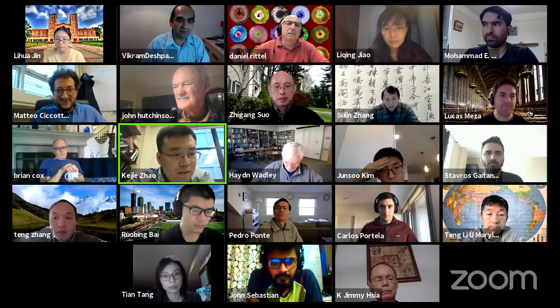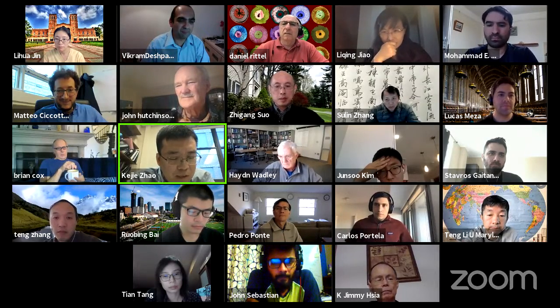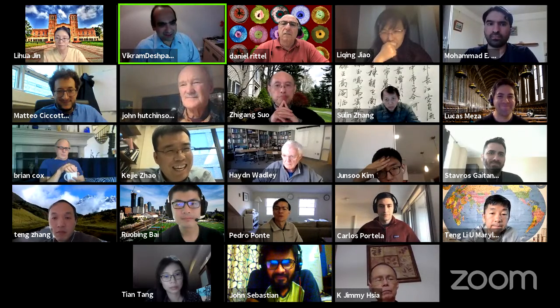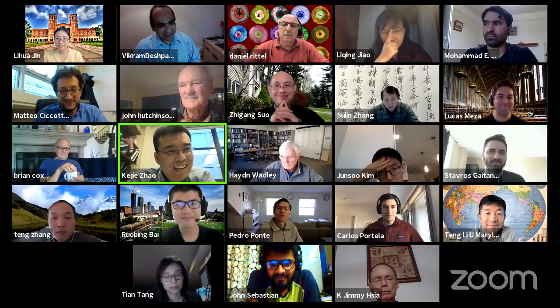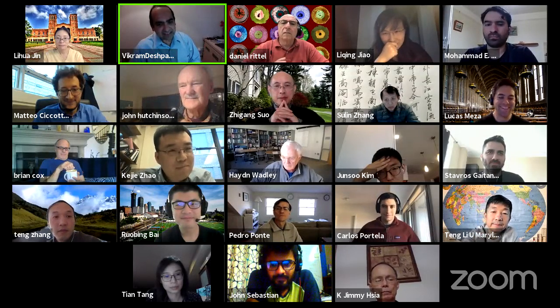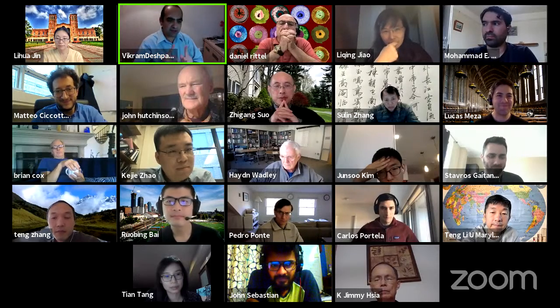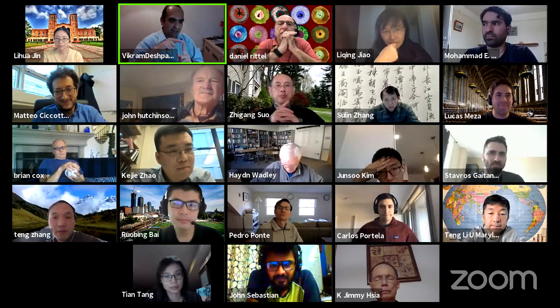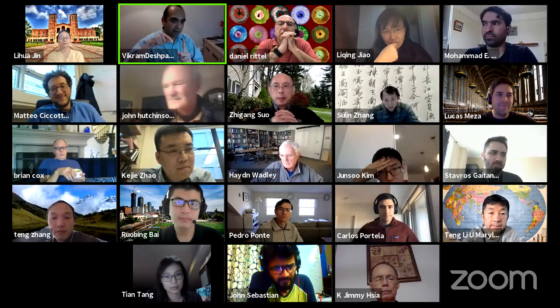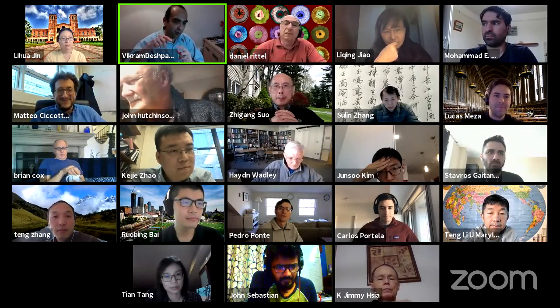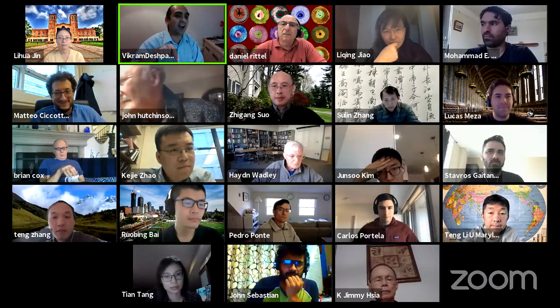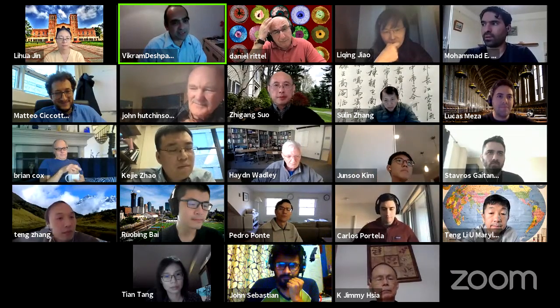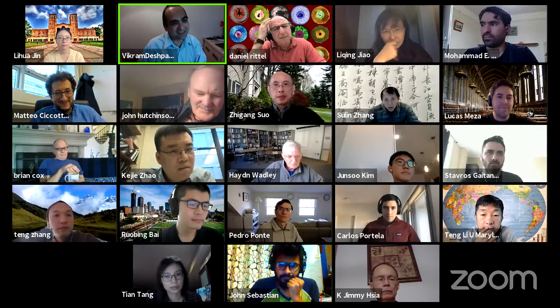Right. So maybe a little more on how that reflection happens, why the shear kinking is reflected. Lucas, of course, will tell you a lot about this because that was his work, but he can butt in at any time. The reason you get reflection is that in a three-dimensional composite, you get a kink across one tow, then it hits another tow where the fibers are in a very different direction and can't kink. So, and I'm saying this qualitatively, it has no choice but to reflect back into the current tow.